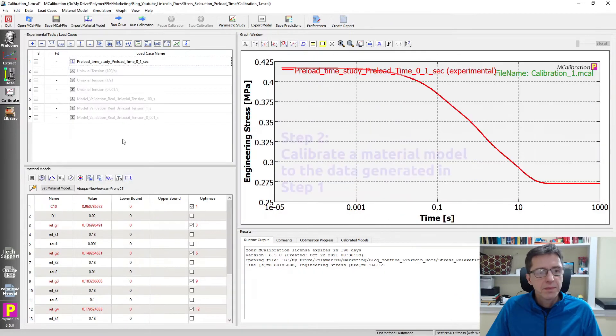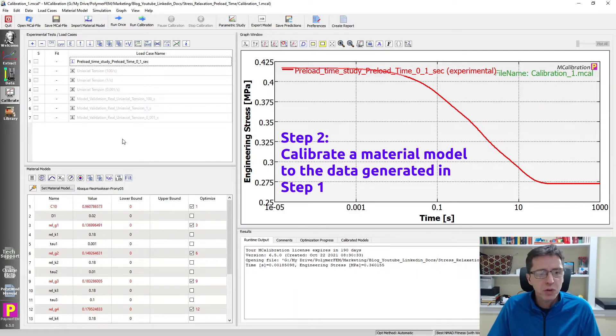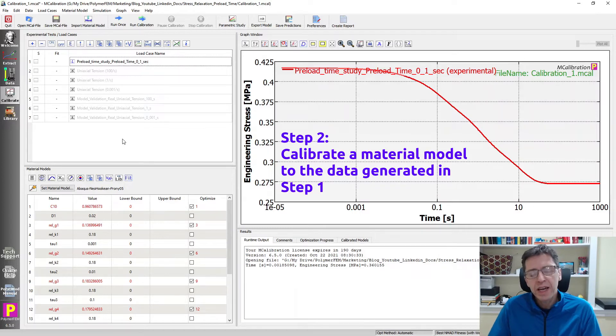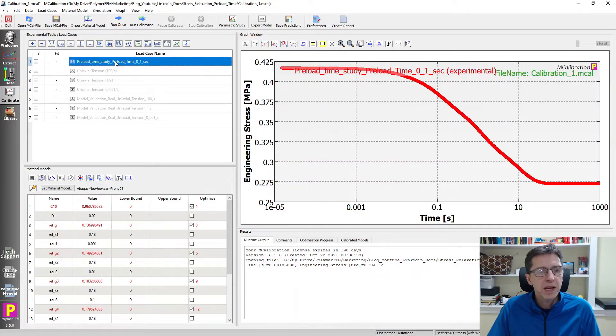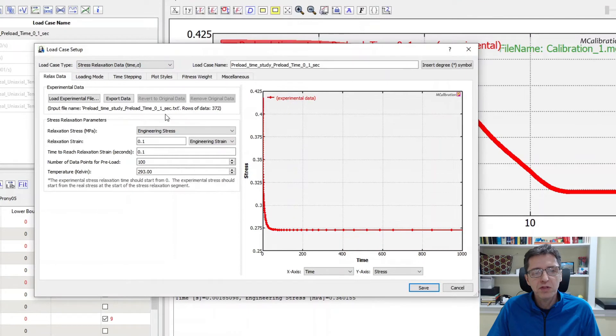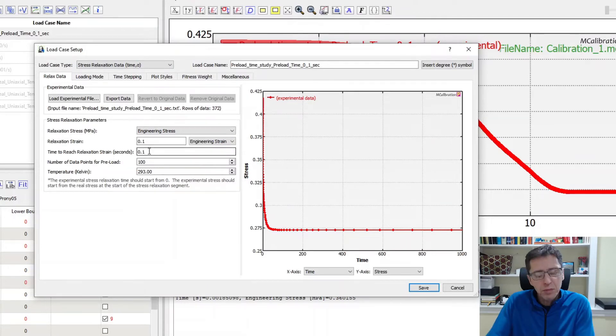That was step number one. Step number two in our study is to take the experimental file that we generated - which we know exactly comes from a very specific Prony series linear viscoelastic material model - and try to find a linear viscoelastic material model by matching it to that data. I already have a load case here - it's a stress relaxation load case - and I've specified the specific file we generated in step one. Here is my stress relaxation segment, occurring at 10% strain. In my first example, the time to reach the preload strain was 0.1 seconds, which is exactly what I used when generating the data.